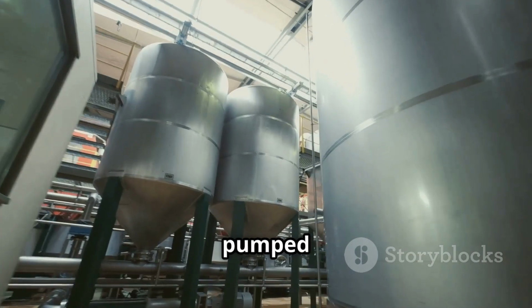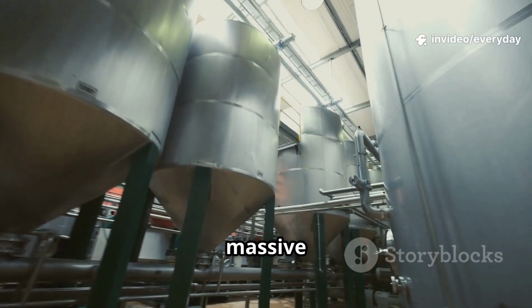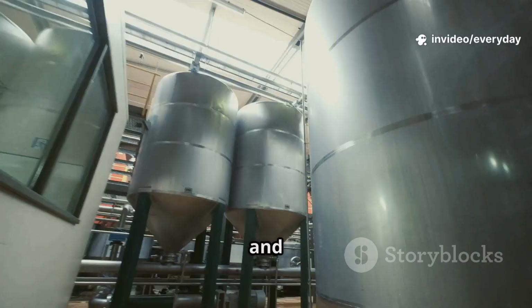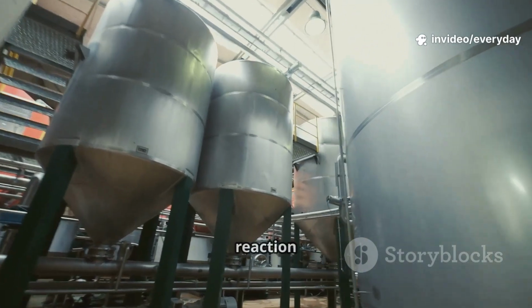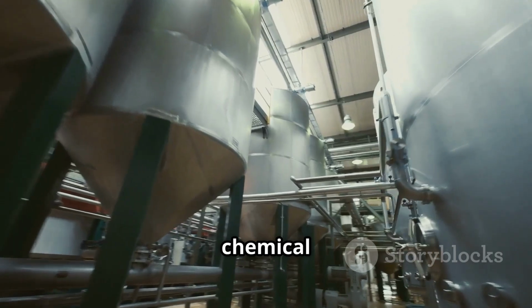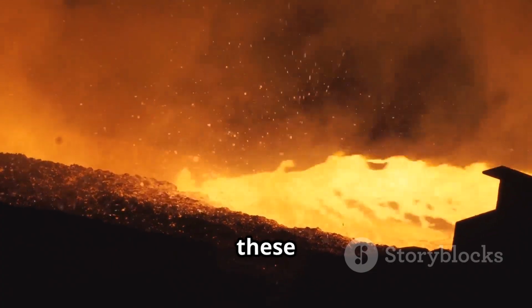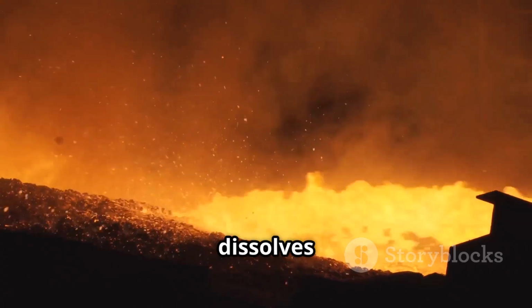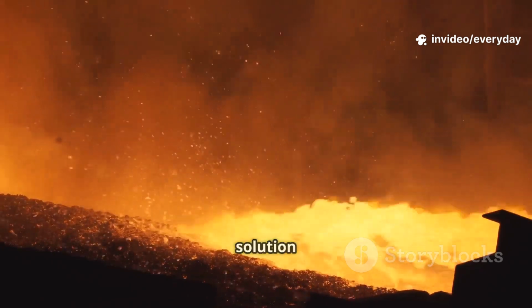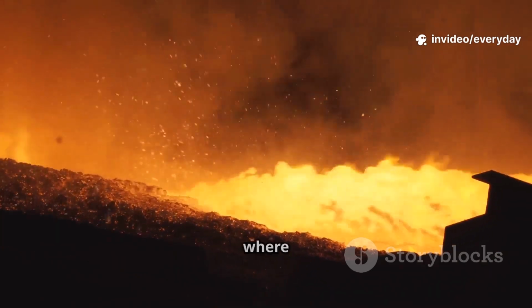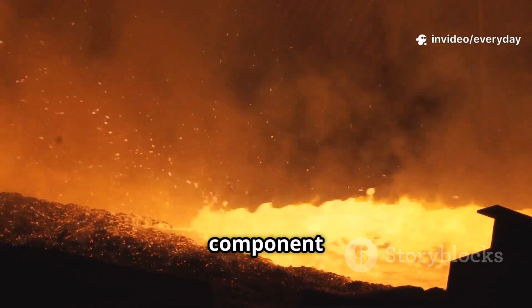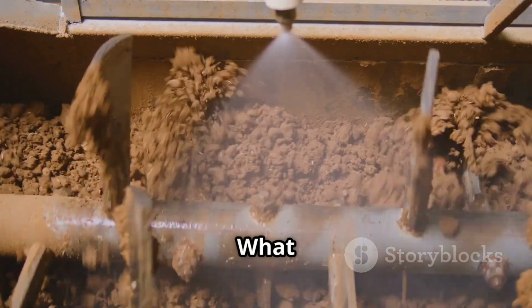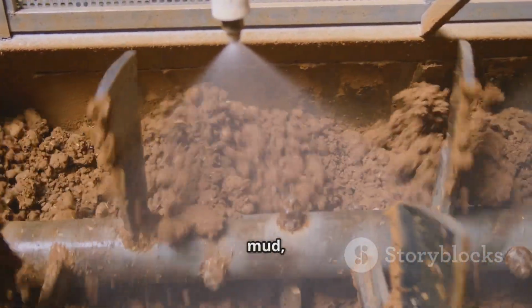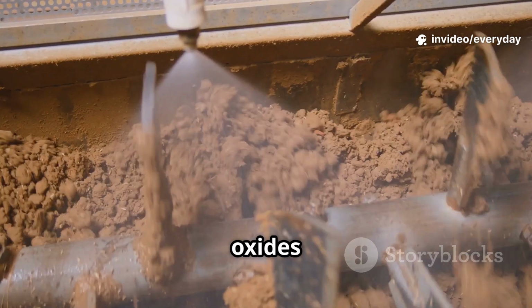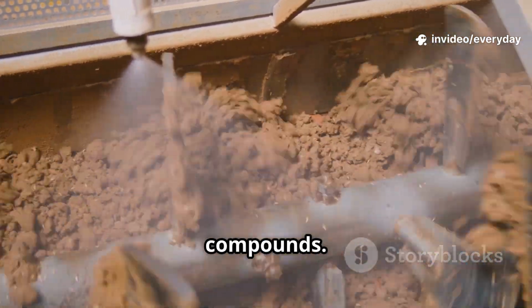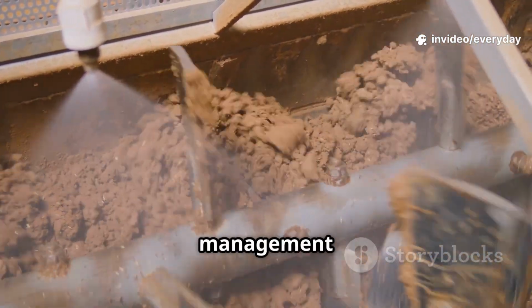The mixture is then pumped into giant digesters, massive steel tanks designed to withstand high pressures and temperatures. These digesters act as reaction vessels, facilitating the chemical breakdown of the bauxite. Inside these digesters, the hot caustic soda dissolves the aluminum oxide, forming a solution of sodium aluminate. This is where the magic happens, as the valuable component is selectively extracted. What remains is a residue known as red mud, a complex mixture of iron oxides and other insoluble compounds. This byproduct requires careful management and disposal.